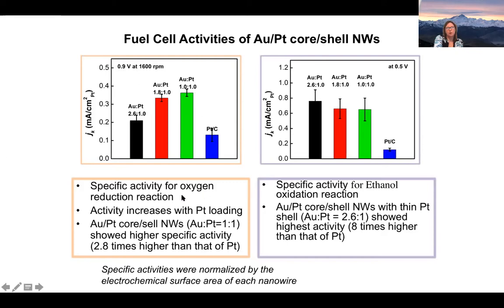One is for the ethanol oxidation, so it's for both parts of our fuel cell. And we showed in one case it was 2.8 times higher than platinum, and the other was 8 times higher than platinum. And so we were showing that something made biologically and through the process of evolution and selection could become better than the control, what was used today.